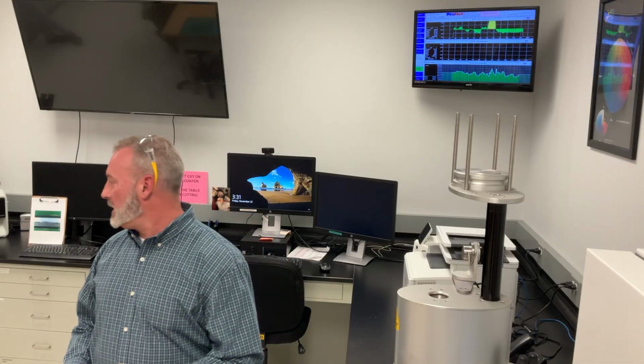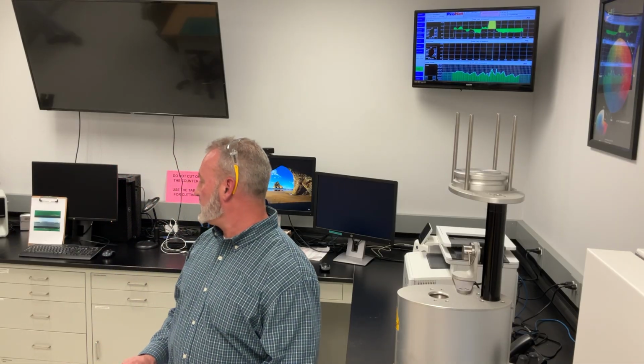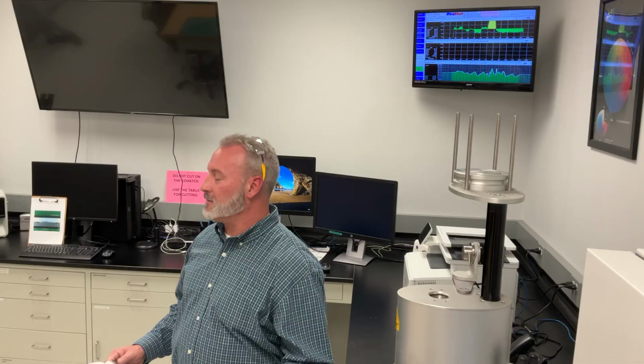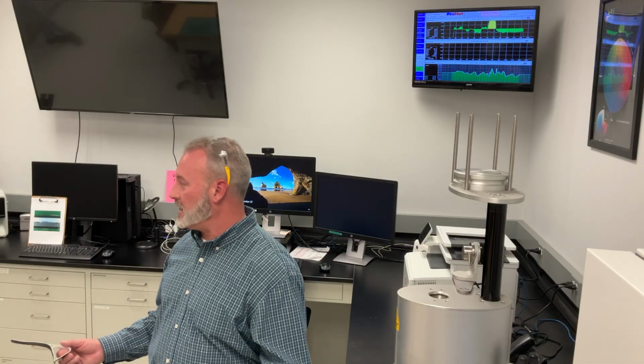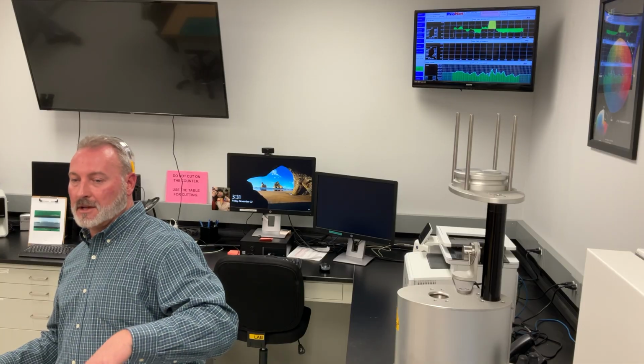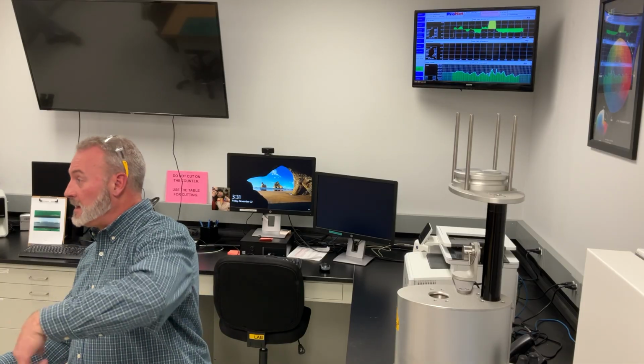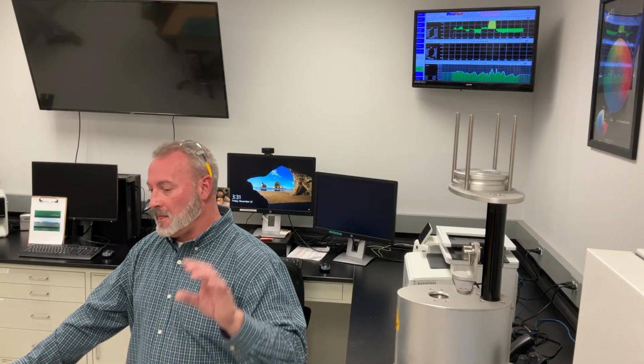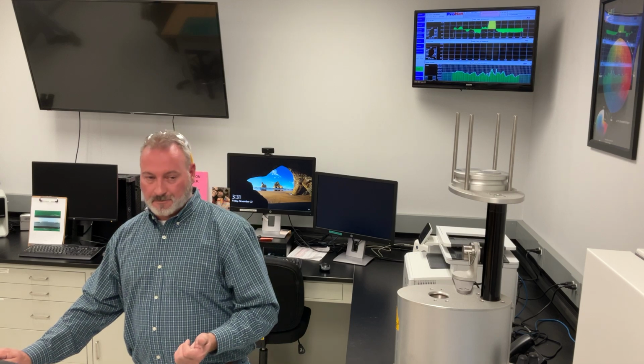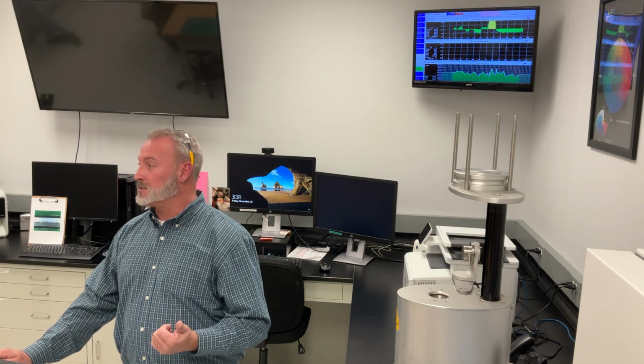As far as the plants, that's about all the testing they do on your product. Except length, width, fastener locations, that kind of stuff, right? But as far as physical property testing, that's what they do. Then on top of that, what we do is that same testing, but we also have a longer term heat aging oven where we put your samples in, we weigh them, we put your samples in for 56 days at 275 degrees. We pull them out and we check them. It cannot lose more than 1% of its weight, and it cannot crack if it's bent over a mandrel.